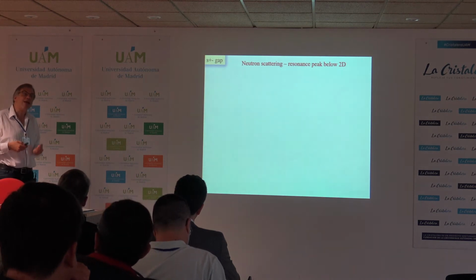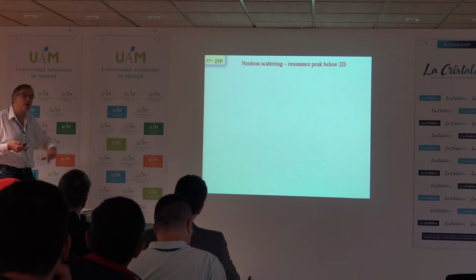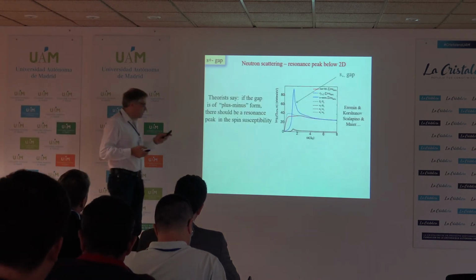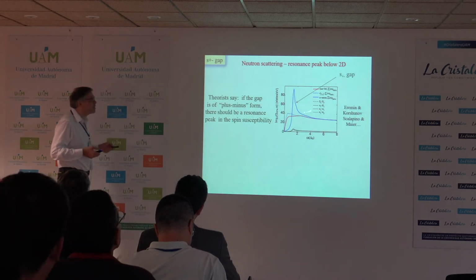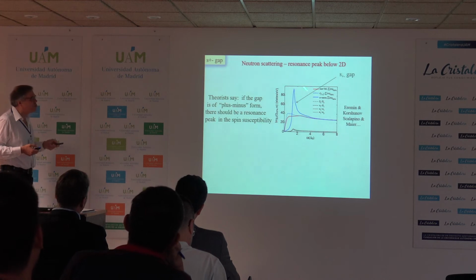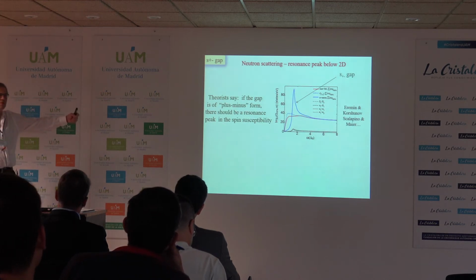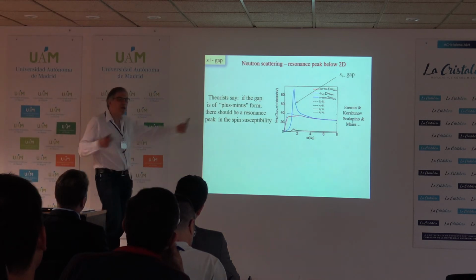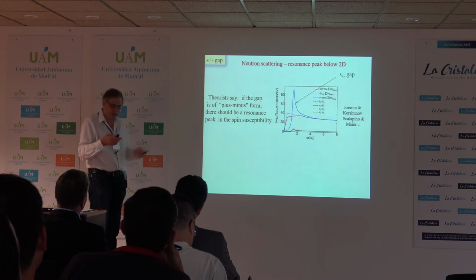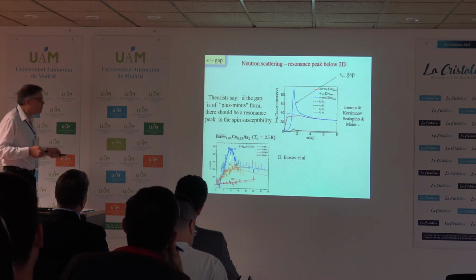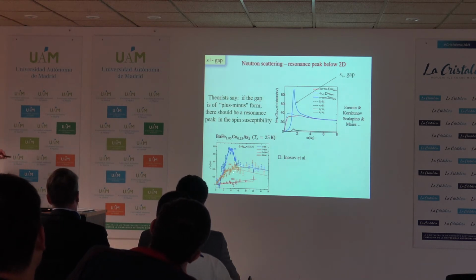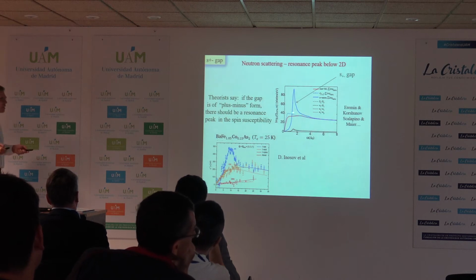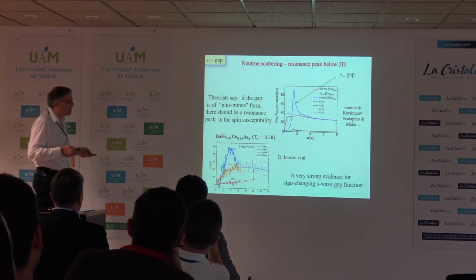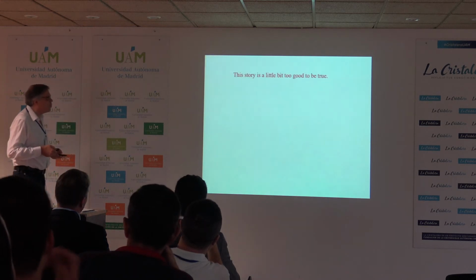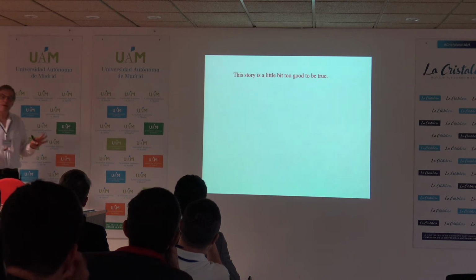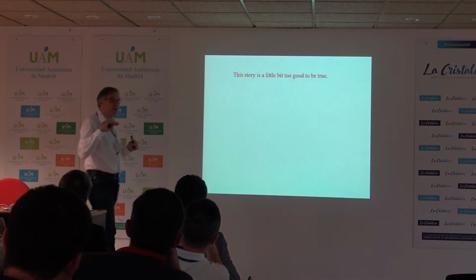And you can also ask, is there any evidence that the gap changes sign between two pockets? Well, there's some evidence. Because if you ask theorists how to distinguish between conventional S and S plus minus, they'll tell you, do neutron resonance, and because there is a sign change of the gap, you will have a peak at the momentum that separates hole and electron pockets, which happens to be pi-pi. So this is the theory picture. In this experiment, they clearly see there is a peak at momentum pi-pi at some finite frequency, which is totally consistent with this picture. So this is one piece of evidence. There's other evidence that the gap really changes sign between two pockets. Let me stop here and say that was really an order zero introduction.